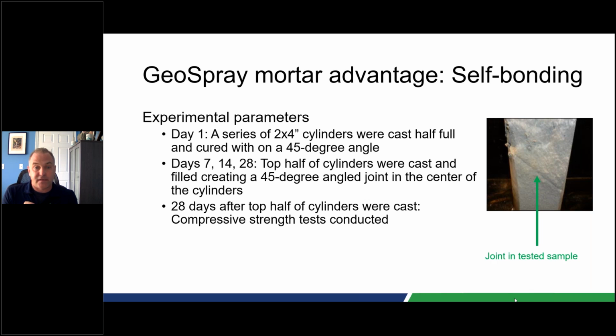One of the main advantages of a geopolymer, and specifically Geospray, in addition to its flexural properties from a design standpoint, is the fact that it bonds to itself really well. People that are familiar with cement know what we would refer to as a hydration chemistry. It brings in water, and that is what holds the material together. If you want to do a quick test, take a piece of cement, put it in your oven, get it up above 212 Fahrenheit, drive off all the water, and the next day it will be a powder. And that's because the water is really holding all of that together. In geopolymers, it's different. The actual molecules react to one another and make a long chain. And when you have a joint, that joint is really still an active reaction site, and you can bring new material in contact with it and react through the joint and get a very strong joint. In this point, we would call it a lack of a cold joint.